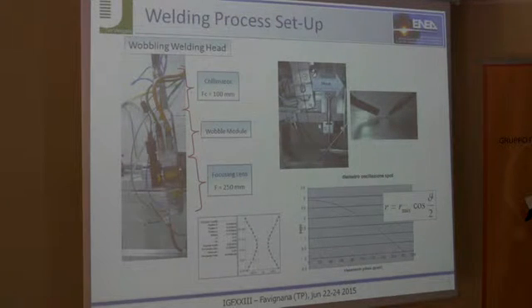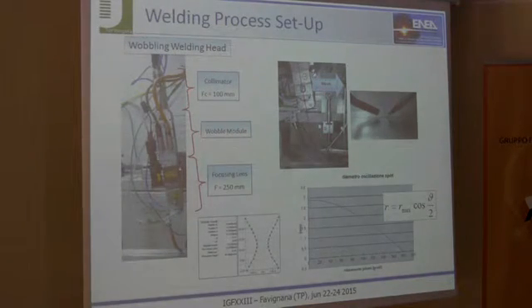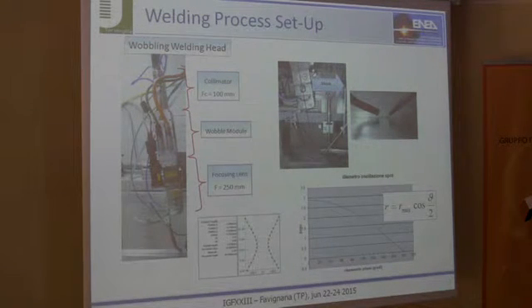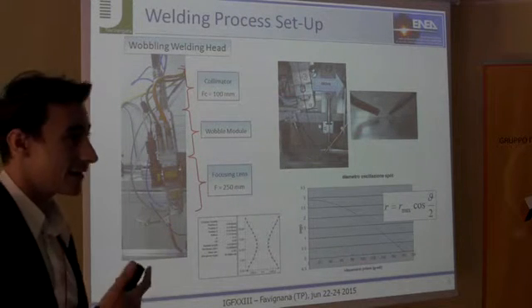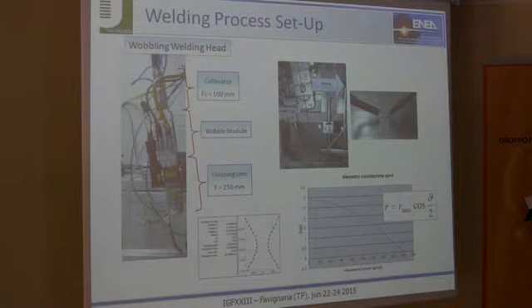Now, what are the challenges of the aluminum laser welding process? The challenges are the aluminum reflectivity, the cracking susceptibility, and the formation of porosity. To overcome these issues, we developed a laser welding process with an innovative wobbling welding head that allows the focal spot rotation and the consequent mixing of the molten bath. This promises a reduction of the weld's porosity, that is the main defect in the laser welding process.